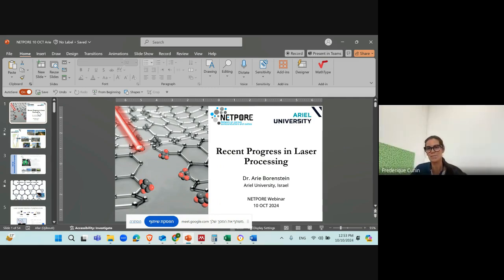Thank you. I get it. So it means that the better the coverage with the functional group, the better the result? Not really. It's a trade-off, because if you have too much of heteroatoms and too few seeds, the laser will just burn everything up, and we remain with almost nothing. This also happens if you use too high laser power. So you have to be very careful with that, but the two components are very important. This is a very precise optimization of your surface.